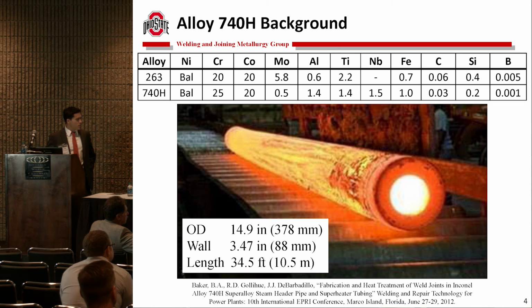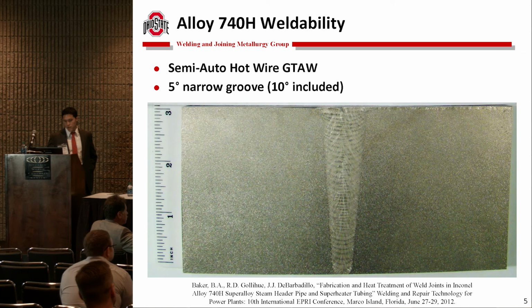This picture here, though, is a big extrusion of alloy 740H, I think one of the biggest extrusions of an alloy of this sort of composition. And this pipe has been sectioned and welded back together with great success, actually. This picture is a thick section weld through that pipe. It's 3 inches thick, with a 10-degree included angle, and it's single pass about 2/3 of the way. And this has been successfully post-weld heat treated, which is pretty encouraging.